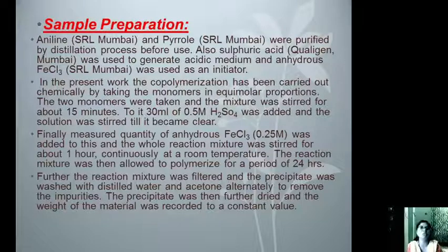The two reactants were mixed and then the mixture was stirred. It was then treated with the acidic medium, that is 0.5 mole H2SO4. The whole reaction mixture was supported by anhydrous FeCl3 salt to initiate the polymerization process. Once the copolymer began to polymerize, we kept the solution for a period of about 24 hours, and after that the sample was filtered out and thoroughly washed with acetone and distilled water and dried.